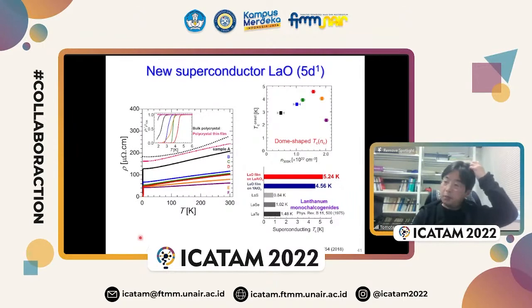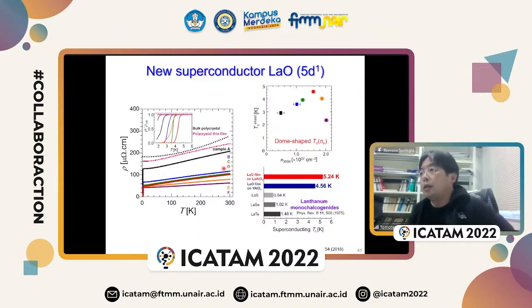And lutetium monoxide, this is a 4F full-shell monoxide. This is also an oxide semiconductor. And the final one is lanthanum monoxide. This has no 4F electrons, but a 5D1 electron. This is a new superconductor. This is the resistivity, and the resistivity becomes 0 at around 4 Kelvin. And this superconducting transition temperature can be tunable by the electron density of this compound.